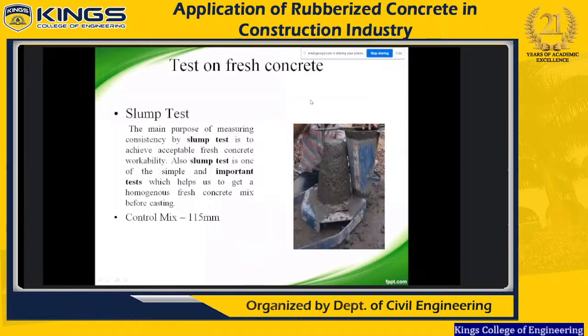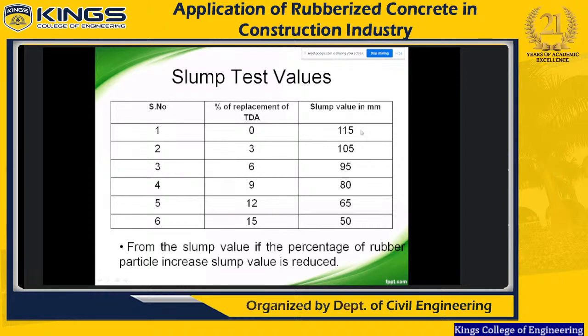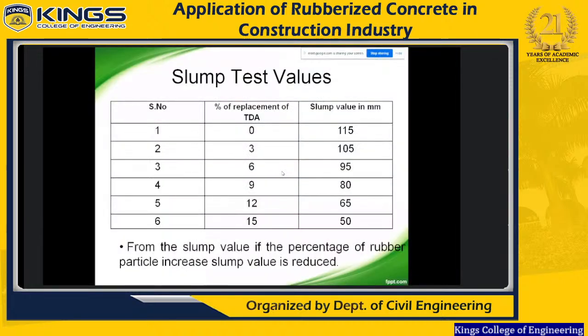The other test we carried out is a slump test for the control mix. So these are some basic tests we carried out for concrete with added tire material. It is the percentage of tire derived aggregates against slump in mm. We observe that as the percentage of tire derived material increases, the slump value decreases. So we need some air entraining agent to add, otherwise the bond between the rubber particles and the coarse and fine aggregate will be minimal, and we do not get a good slump value.